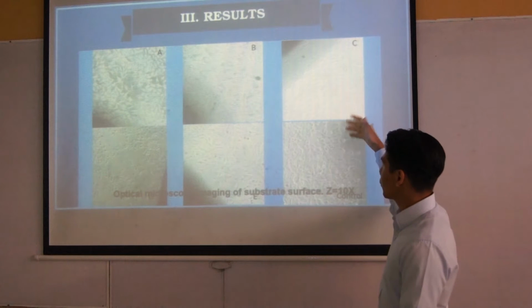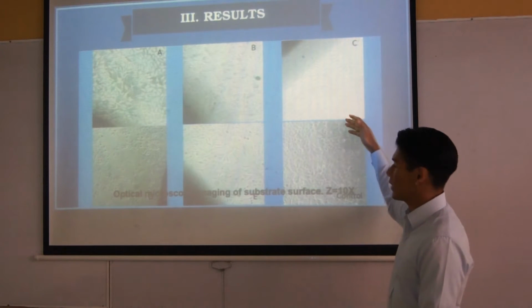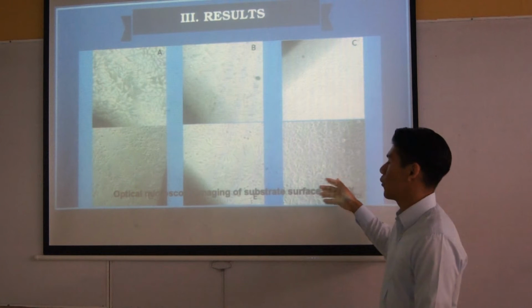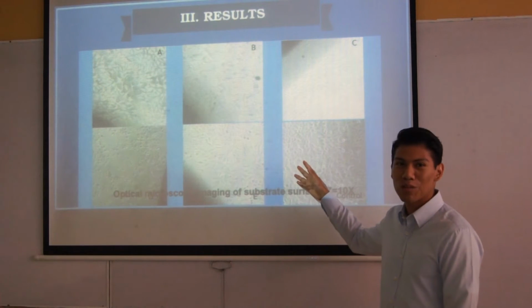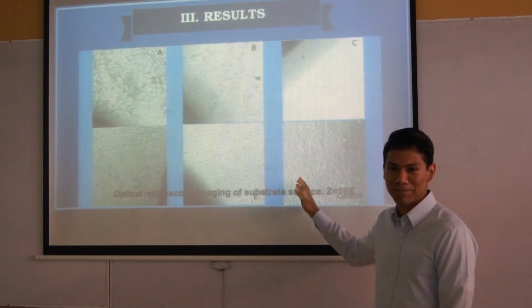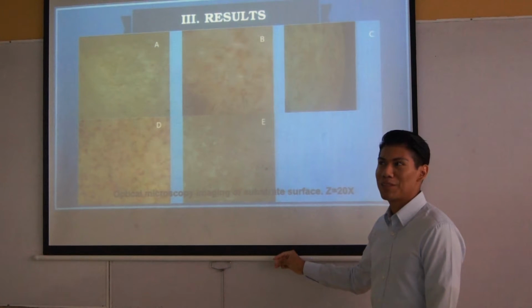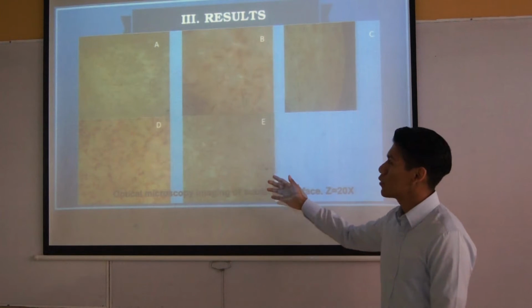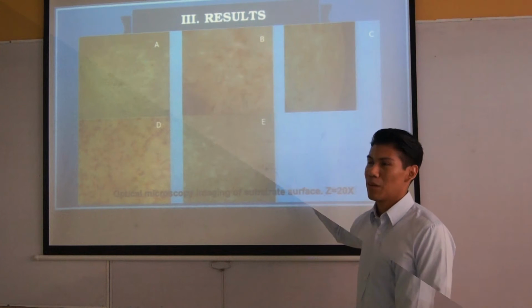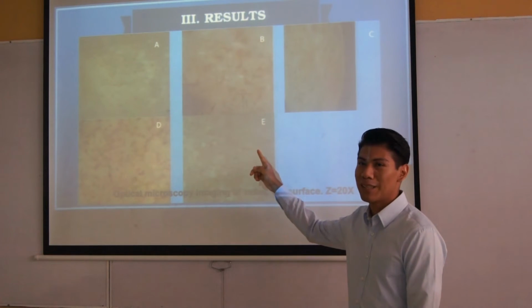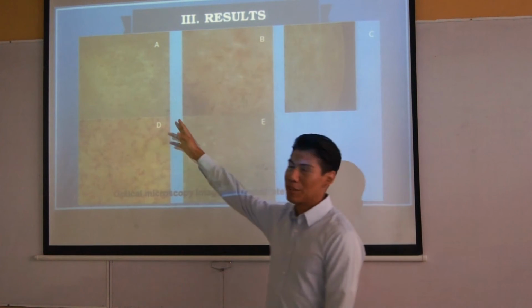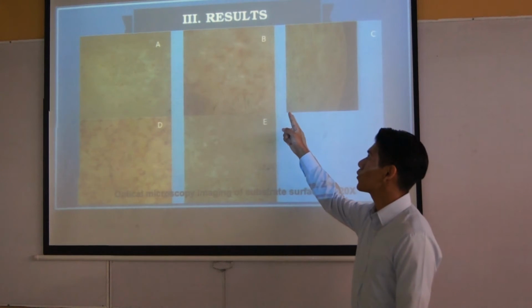If we compare the control to probe C, we see that there's almost no difference, and we cannot tell there is a difference. The control substrate is polystyrene. This is a microscopy imaging of the different surfaces in the substrates. We have surface A and B that has a lot of dead material, and also in substrate B.